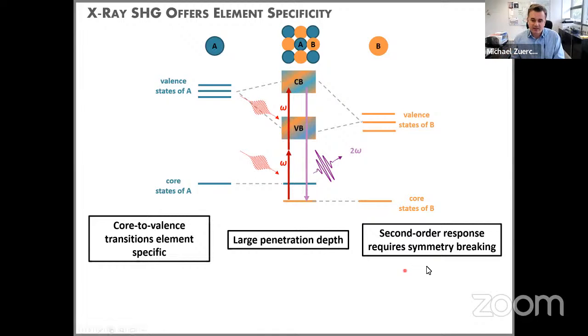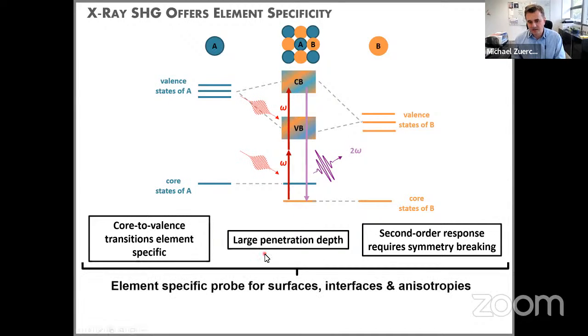And the other thing is, of course, symmetry breaking. If we can do these measurements, we can actually measure symmetry-breaking states, so that can be the surface, a buried interface, but also systems that inherently break inversion symmetry. And I will show you a few examples along today's presentation where we achieved some of these properties and actually did measurements in physical systems.